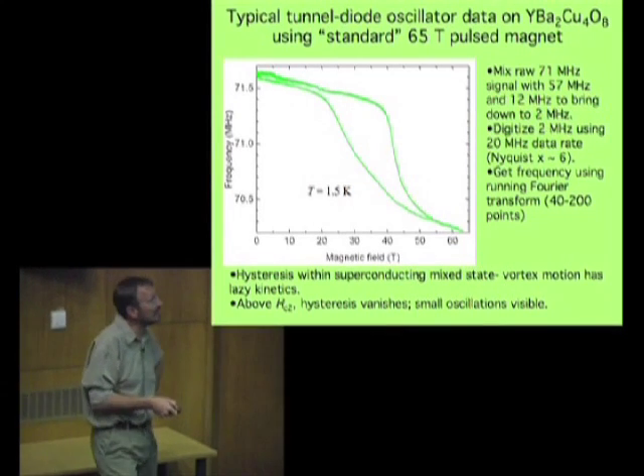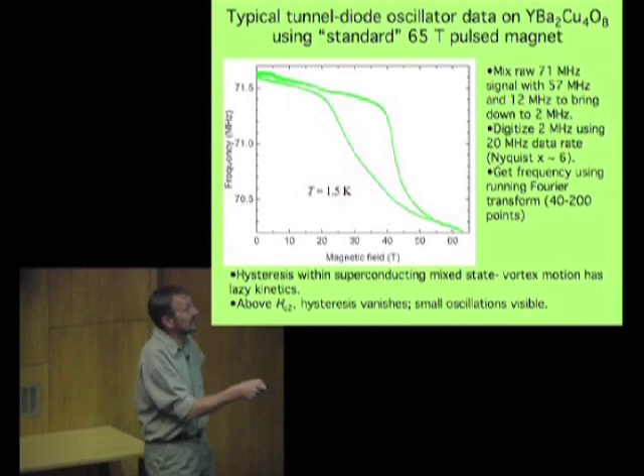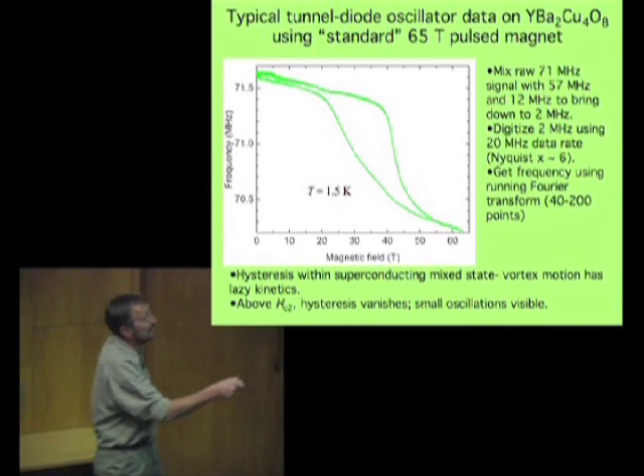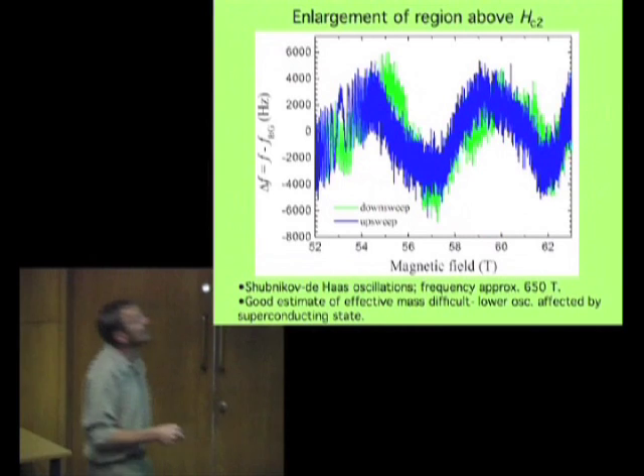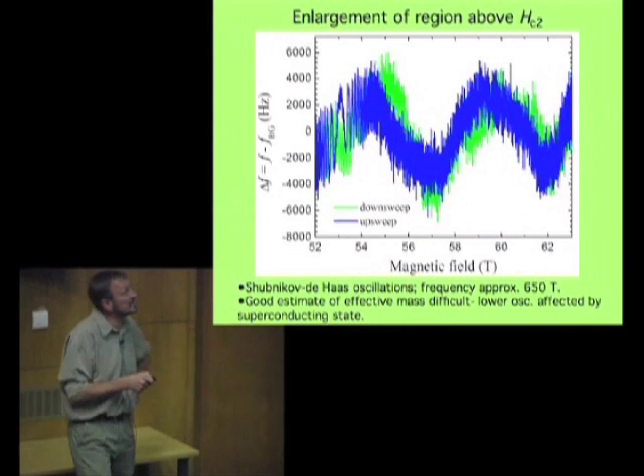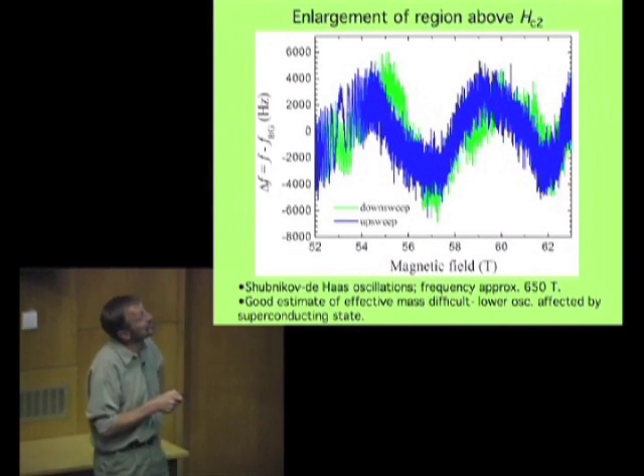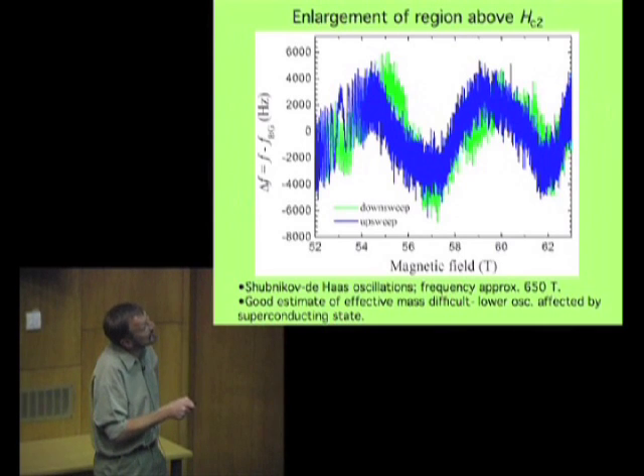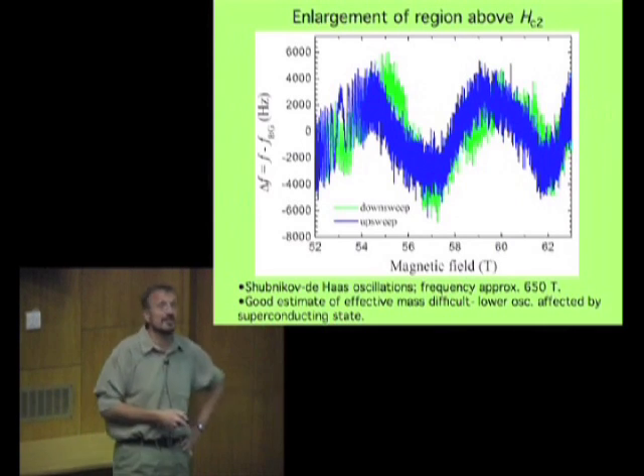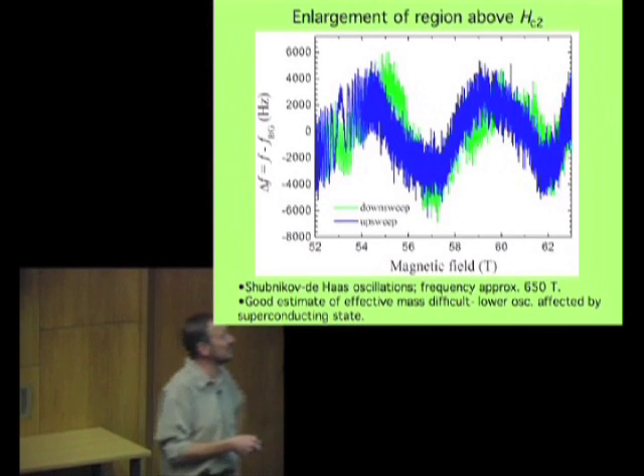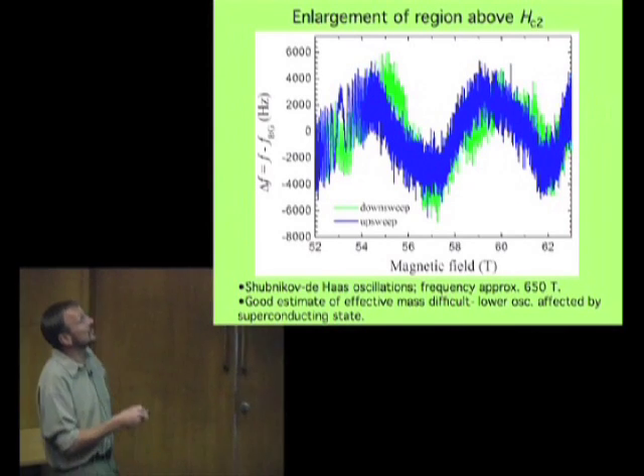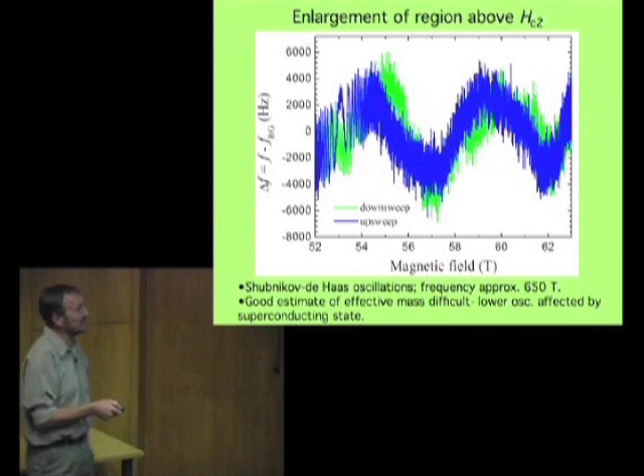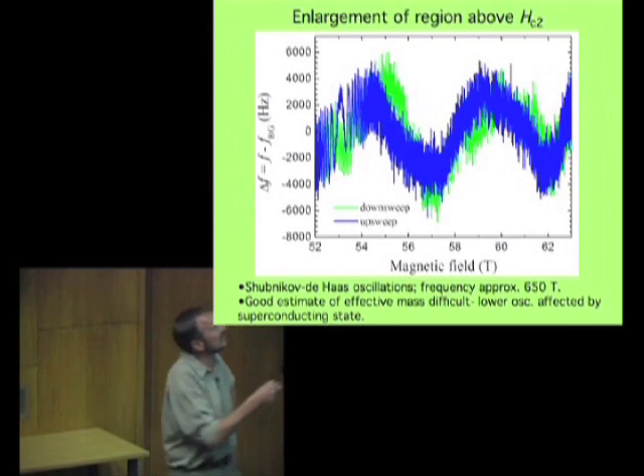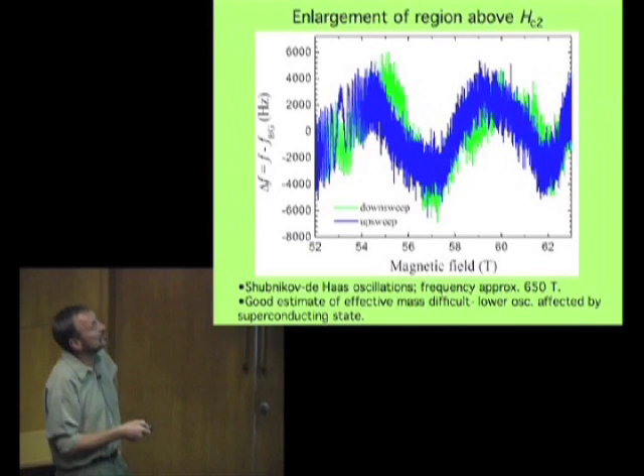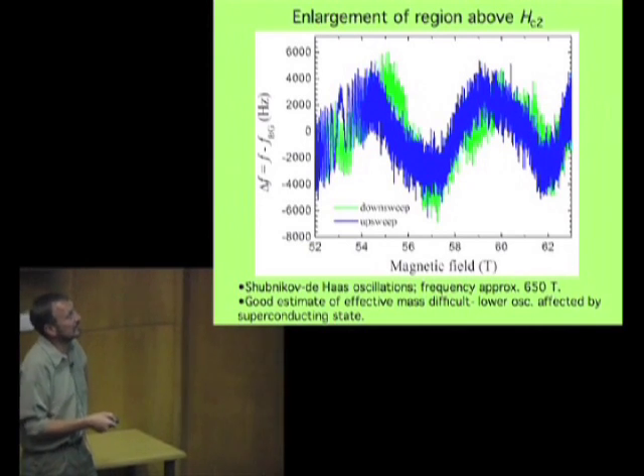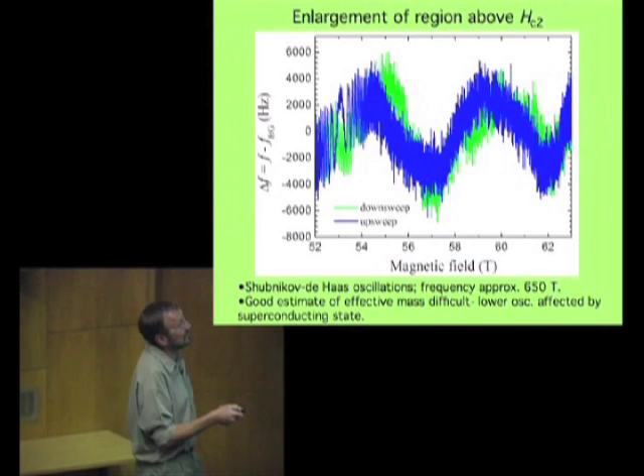So what we have to do now is look at this small part here and see what we can see in the normal state. This is the normal state of the superconductor. And lo and behold, this is raw data. These are raw data with the background subtracted. This is the frequency. You can see that the frequency and therefore the conductivity is oscillating with the Shubnikov-de Haas oscillations. But we only get 2 oscillations in this particular superconductor, which means that we can't estimate the frequency very well, nor do we have much leeway in doing things like temperature dependence so that we can see the effective mass.